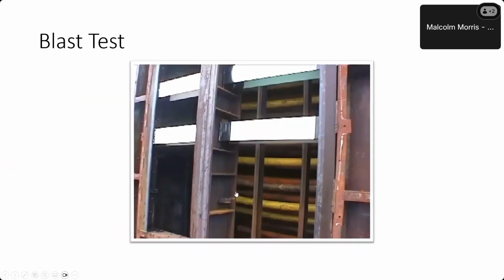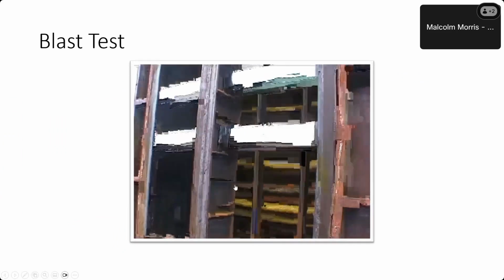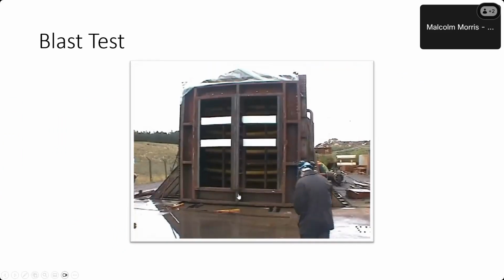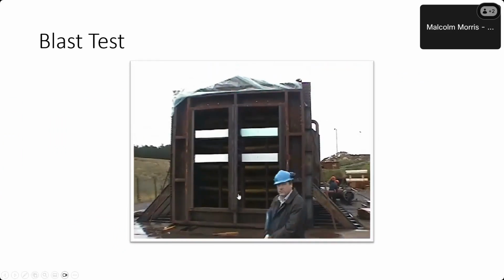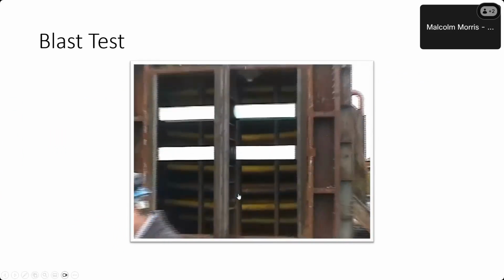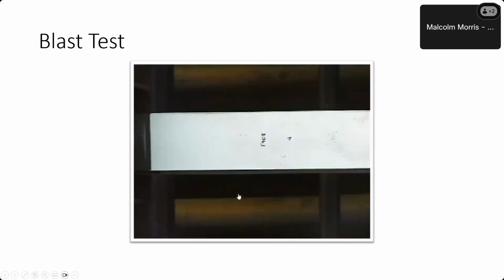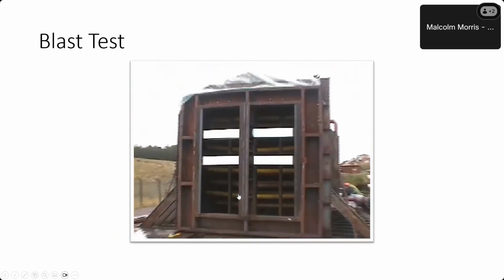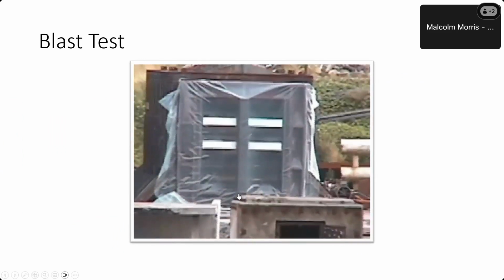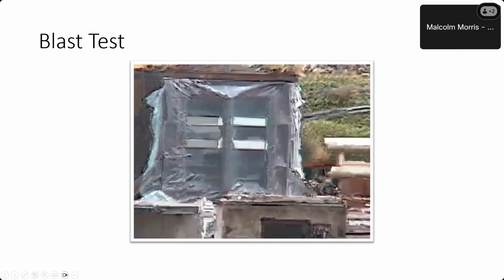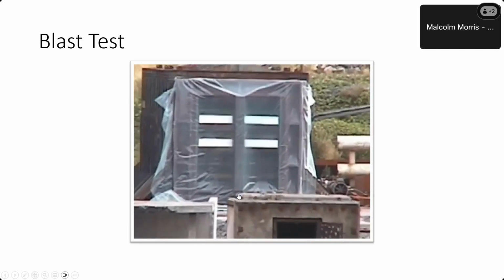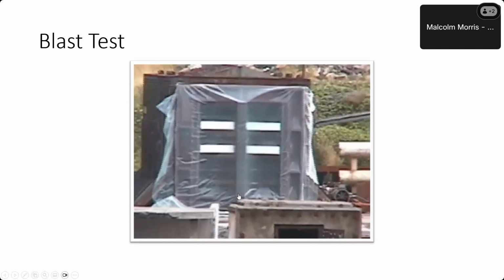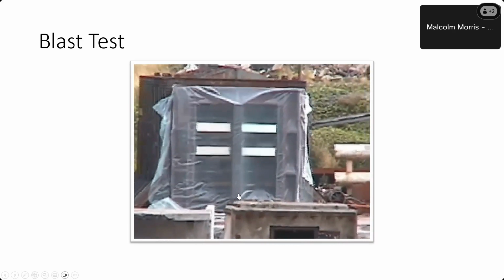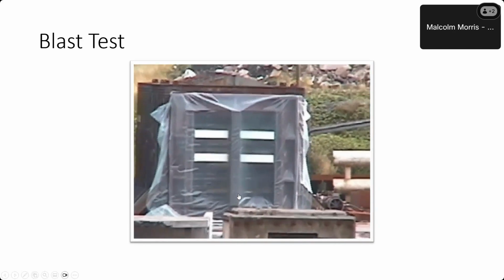This is what they call a blast test. Effectively, this test proves what would happen in the event of an explosion preceding a fire, because if there is an explosion, then what you don't want is for the blast to blow off the fire protection coating, and it all ends up on the floor. So this is done at an external test house, where the beams are set up at the end of that container, which is filled with a gas and air mixture, which will shortly be torched, and there's an enormous pop and bang. People have retreated to, there it goes.